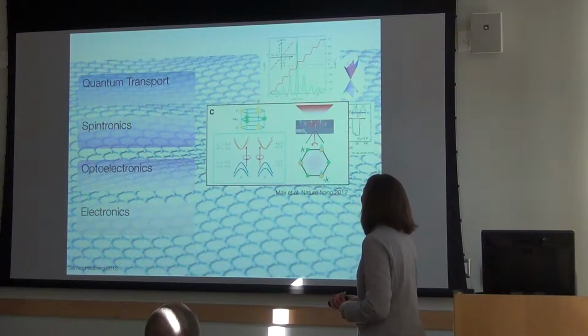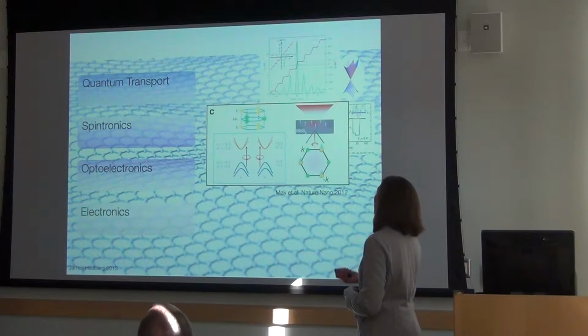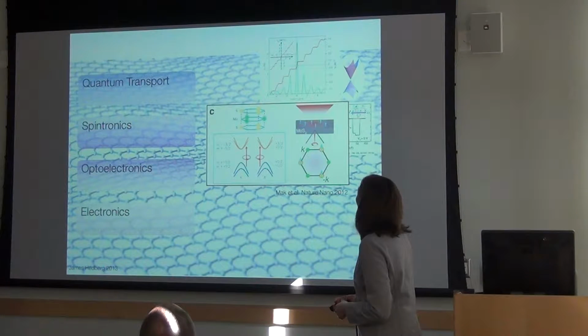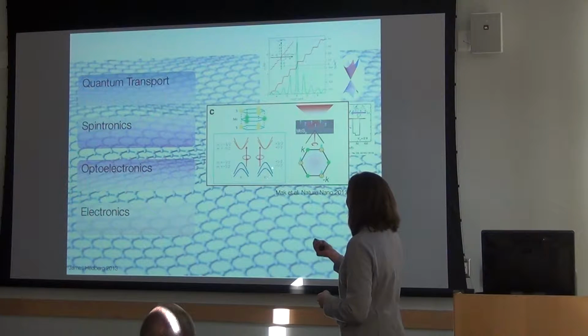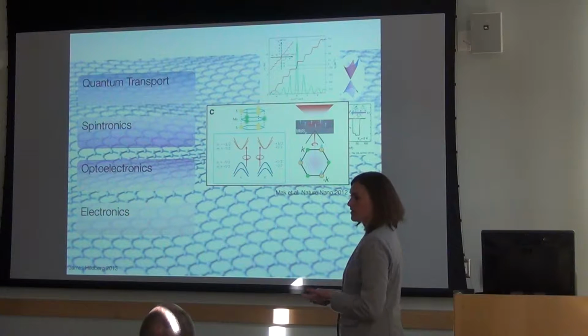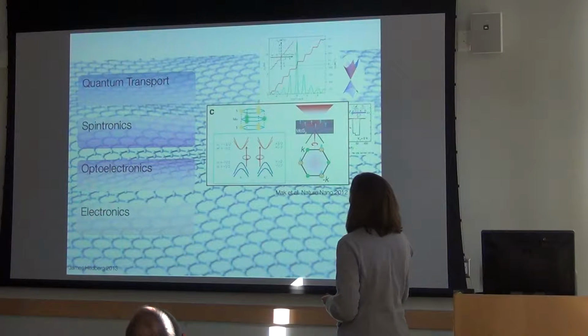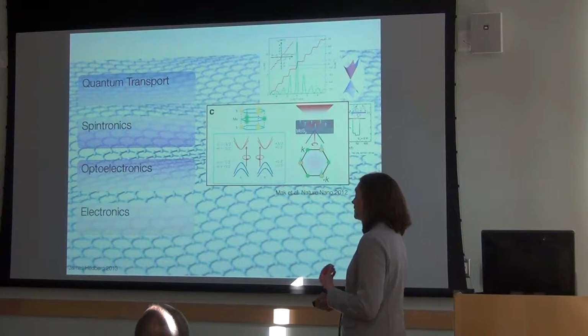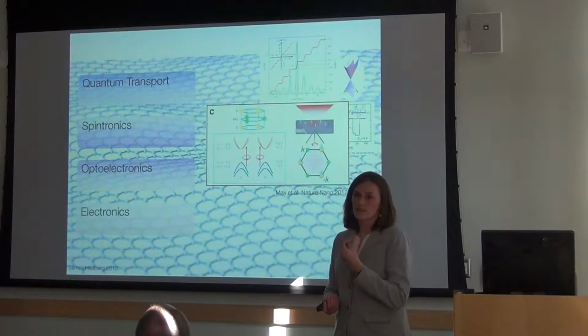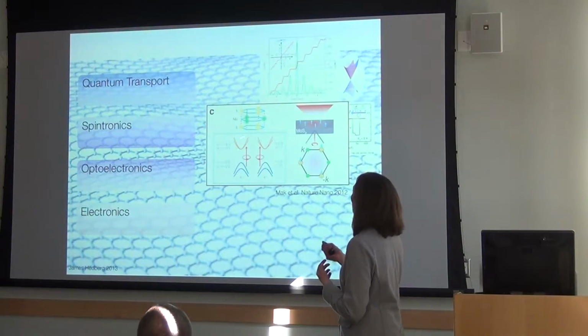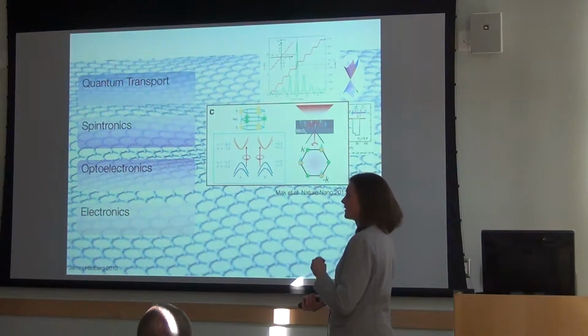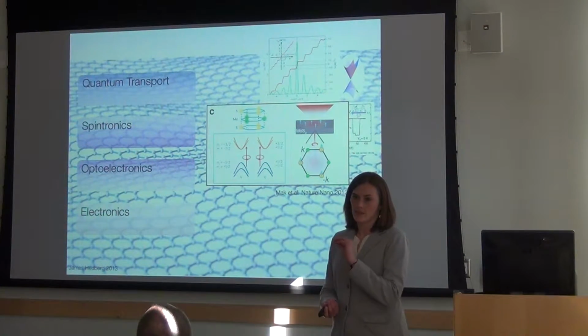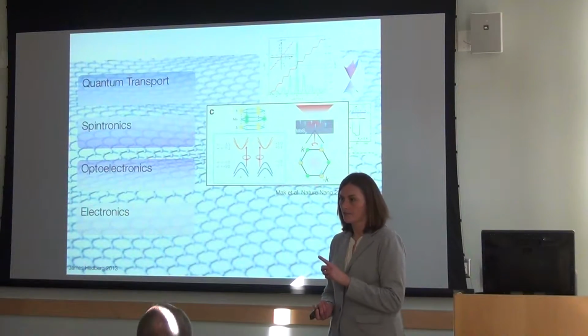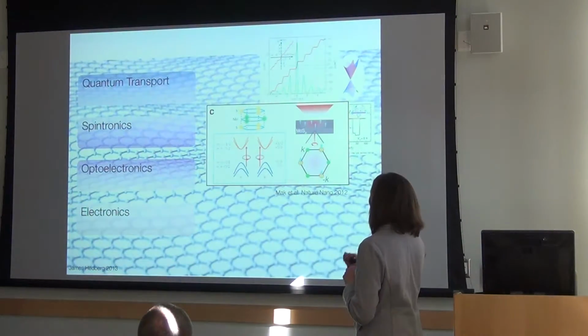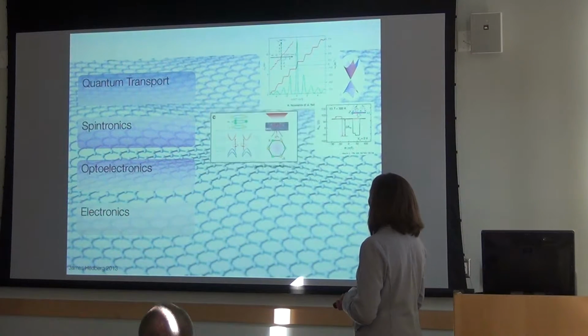And this is an example from optoelectronics in a different material. This is molybdenum disulfide. Because of the band structure of this material, it's a semiconductor, but it also has a spin polarized band. So using the circular polarization of a laser, you can selectively excite electrons of a certain spin direction. That's a pretty interesting feature in that material.